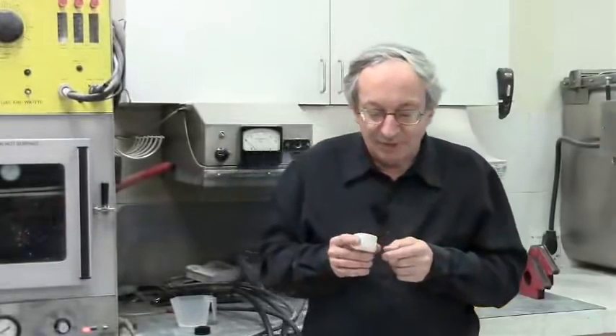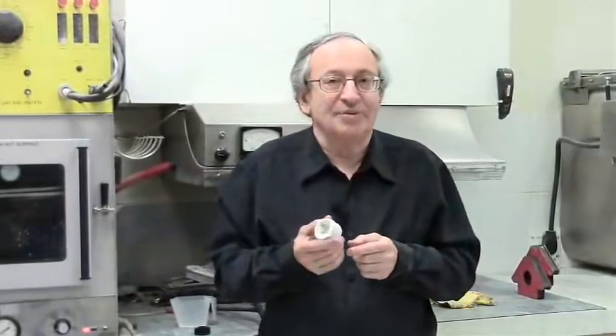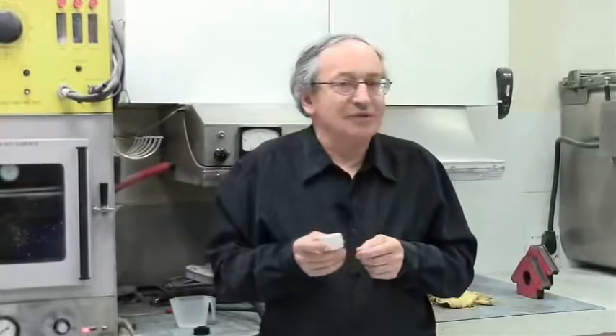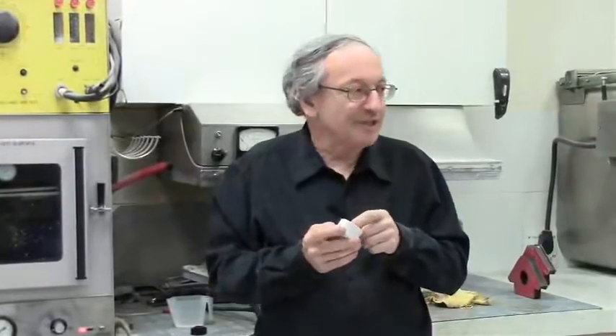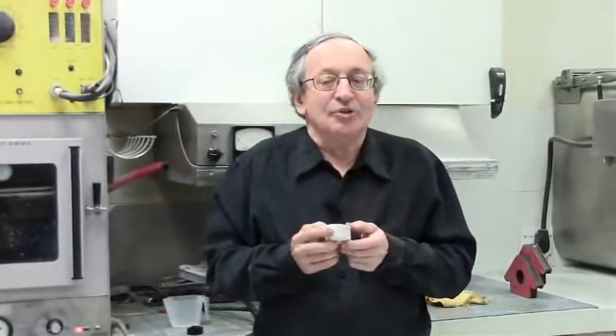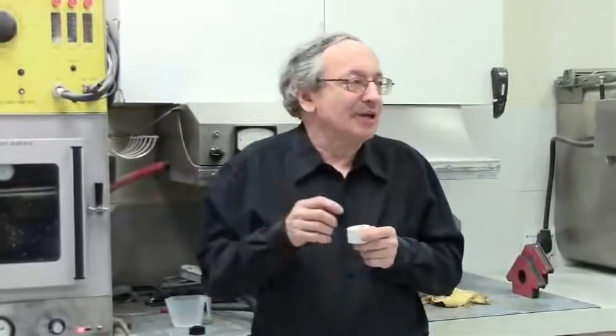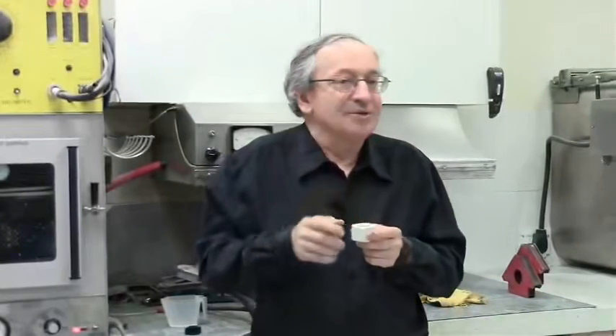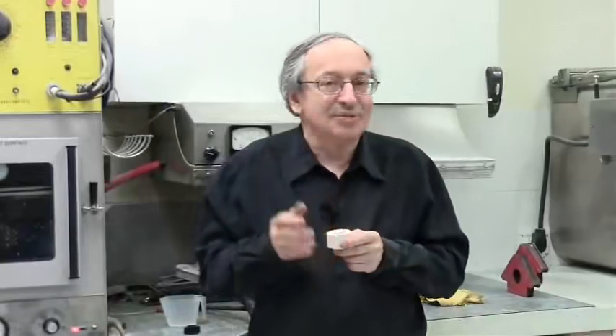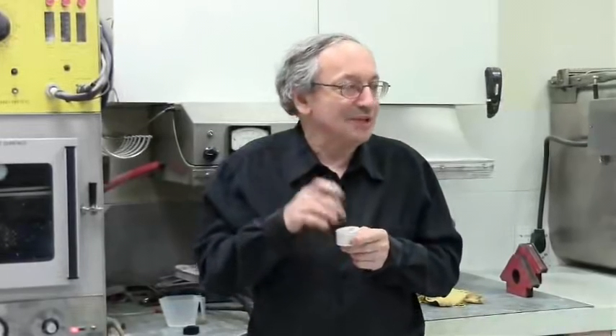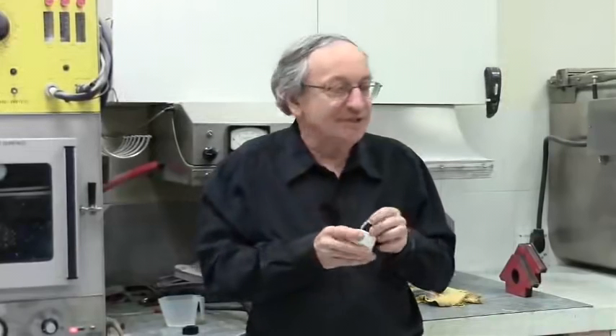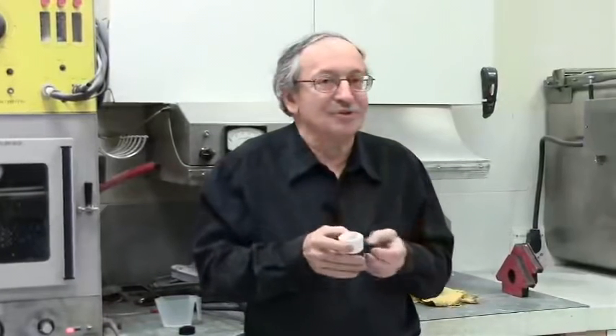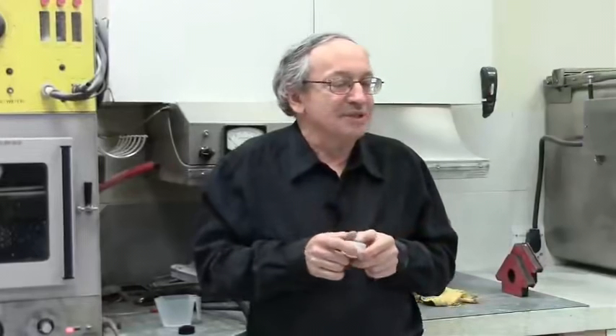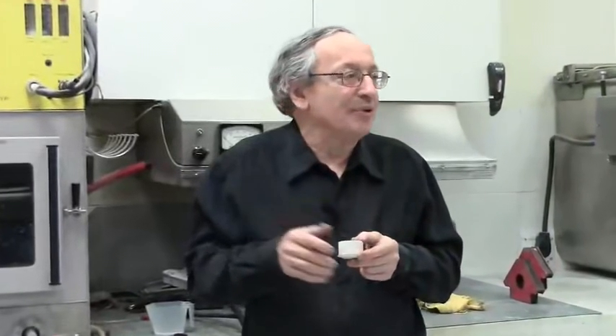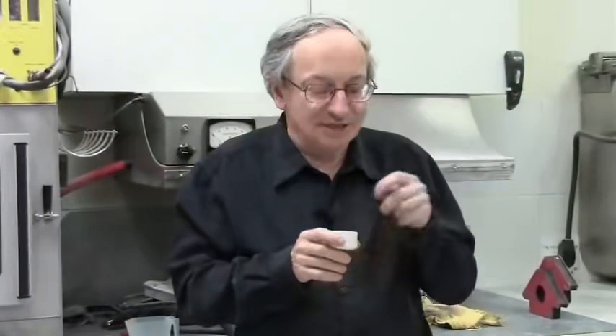Now, a very interesting property of silicone is that short term it can take very high temperature. So if you made this mold, especially if you made it from red silicone, which is higher temperature, you can easily melt zinc alloy parts and pour the molten metal into that. Even some aluminum alloys can be poured into it once or twice, but it ruins the mold. If you use it for plastic, you can make hundreds of parts with one mold. If you use it for metal, maybe you can make 10 parts. But there is a common zinc aluminum alloy used for die casting, and you can cast parts in the silicone from this alloy, and they look perfect, just like die cast parts.